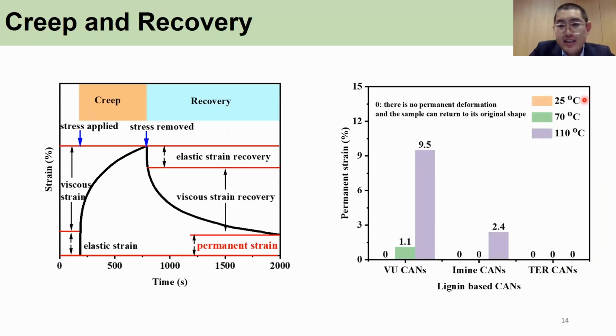And creep is a double-edged sword for the CANs material. On one hand, we want the material to have the dynamic exchange properties, but on the other hand, we also want the material to remain stable at a higher temperature. So looking at these results, the vinylogous urethane kinds and the imine kinds inevitably show permanent deformation when the temperature increases. Well, for the transesterification kinds, because of the irreversible bonds formed, it shows a stable anti-creep performance.